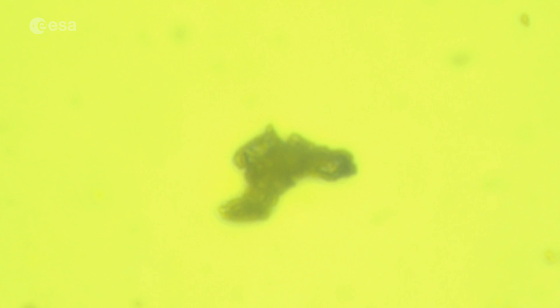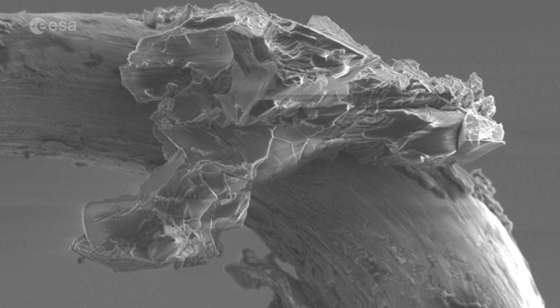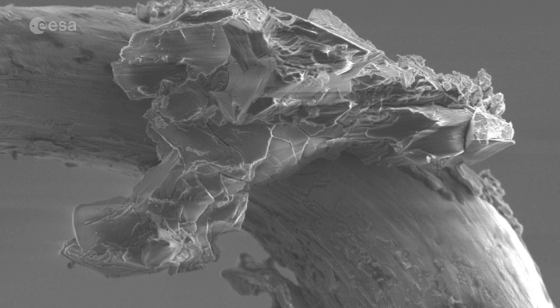So what do the grains actually look like? First of all, they are very small — the samples we have are about 10 to 20 micrometers in diameter, though Hayabusa samples go up to several hundreds of micrometers. When you look at them, they have a very inhomogeneous structure with very sharp edges, because they have not been weathered by water or eroded by friction the same way as Earth particles are. You also have micro cracks on the surfaces, so they are not like one block. And there are nano craters on them as well, which is a witness of the fact that they have been exposed to the outer environment, a bit like all planetary bodies in space have craters at their surface.